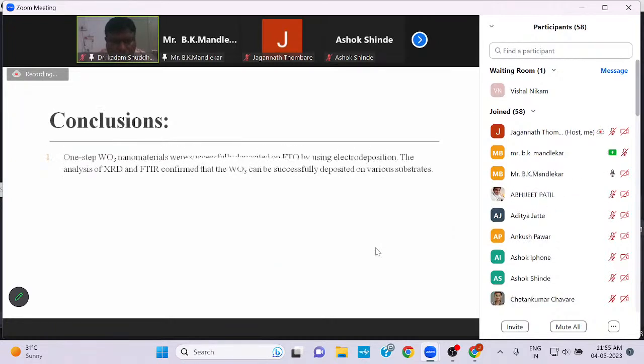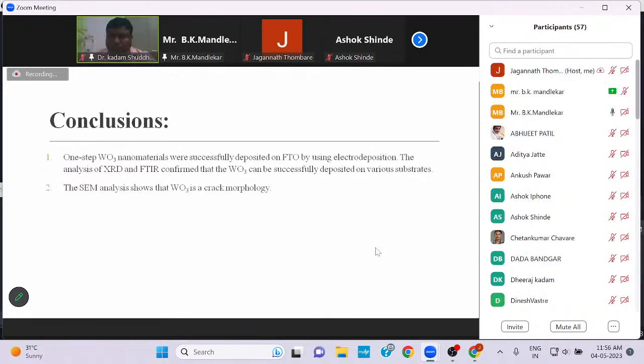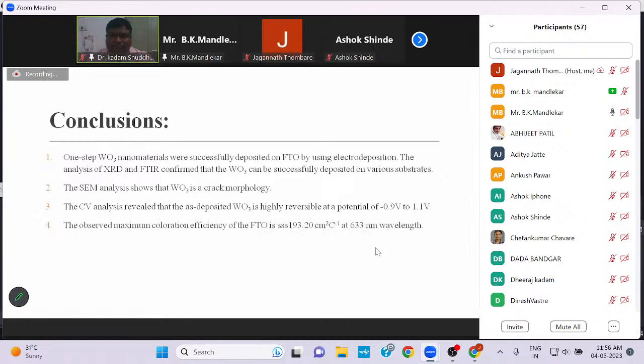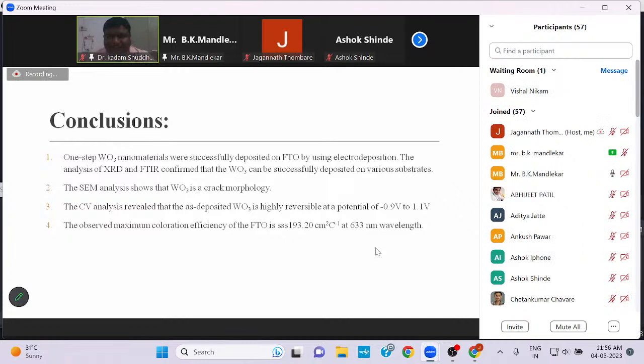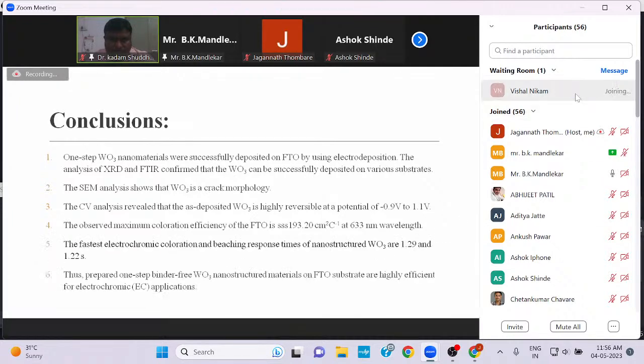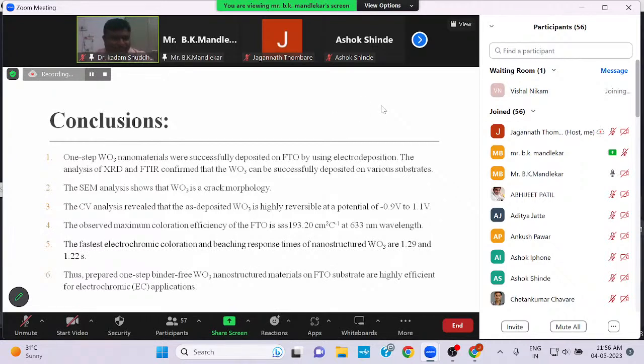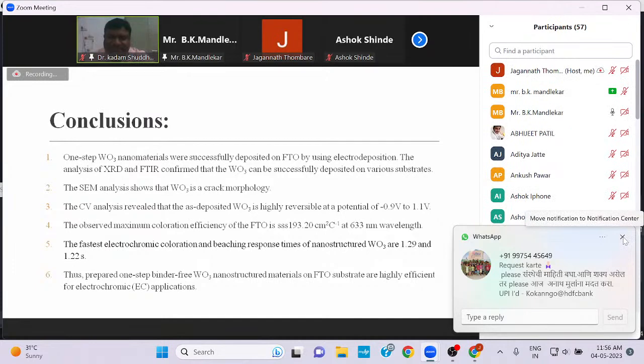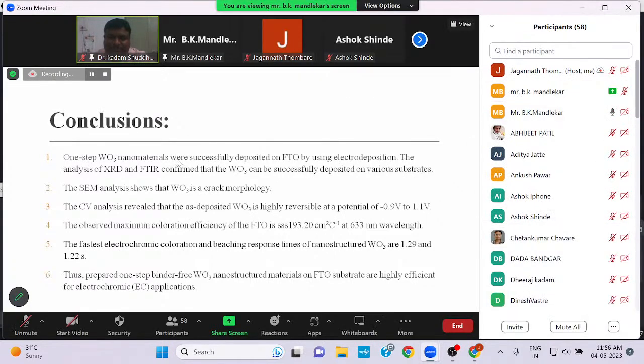In conclusion, one-step WO3 nanostructures were successfully deposited on FTO by using electrodeposition. The XRD and FTIR analysis confirmed that WO3 can be successfully deposited on various substrates. The SEM analysis shows WO3 has a crack morphology. The CV analysis revealed that as-deposited WO3 is highly reversible at potential -0.9 volt to 1.1 volt. The observed maximum coloration efficiency of FTO is 193.2 centimeter square per coulomb at 633 nanometer wavelength. The fastest electrochromic response times of the WO3 nanostructure are 1.29 and 1.22 seconds. Thus the one-step prepared WO3 nanostructure material on FTO is highly efficient for applications.